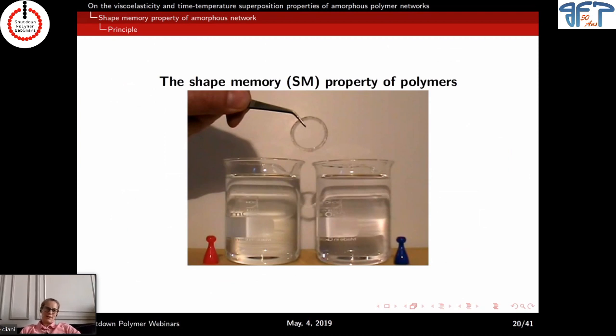You have the length of the chains is the length of your crosslinker. And what's nice with the acrylate for us is that we were able to tailor the glass transition temperature, according to our need in terms of behavior and experimental setting. It's interesting that with something very simple we can change a glass transition easily. Okay. Yeah, go ahead, Etienne.